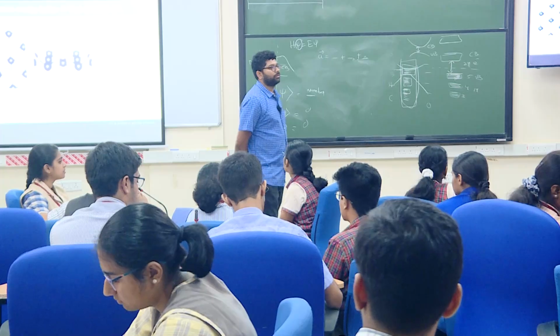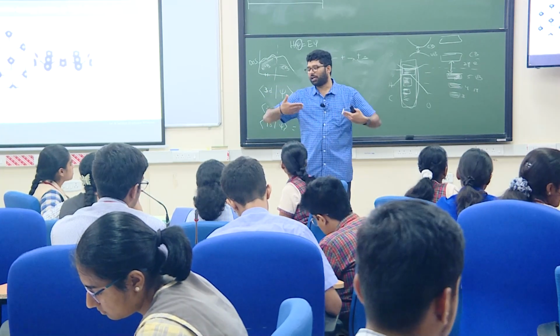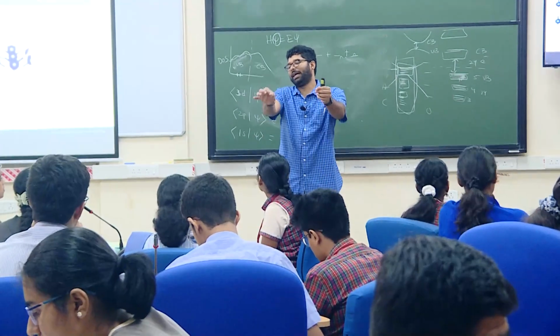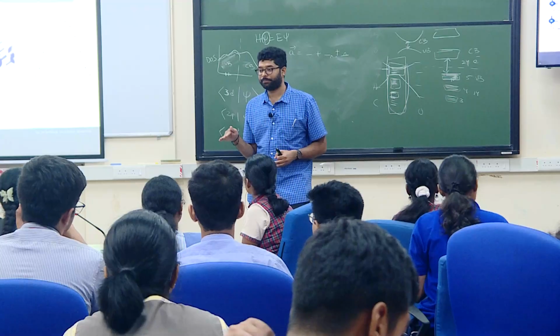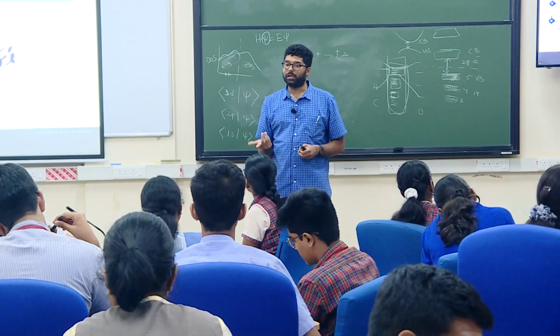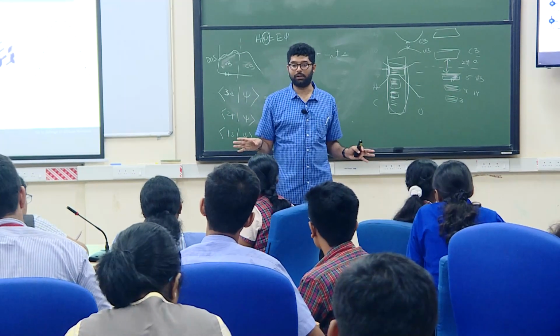Again, the number of layers, you will just load. Loading is not a bad word. You will adsorb more layers. It's not a big deal because all I need to do is place the atoms in those positions. I need to identify how many layers I can adsorb. That is what I am trying to see. If the adsorption energy itself is becoming positive, then I am stopping there. Why am I doing that? As I said earlier, energy going negative always means stable.